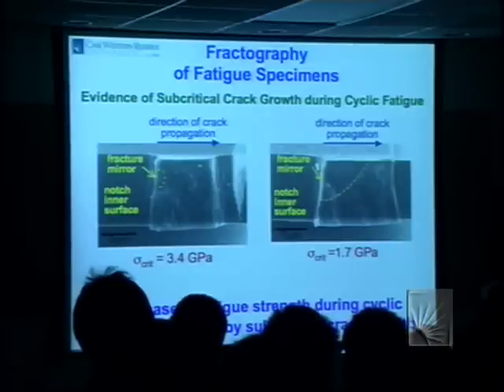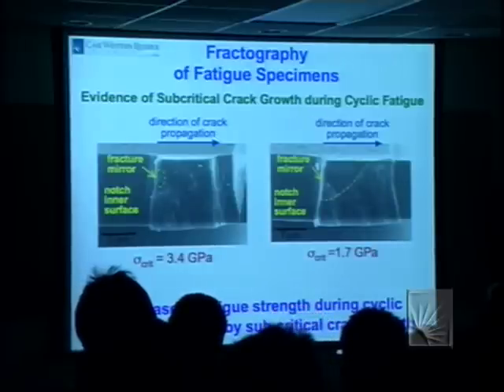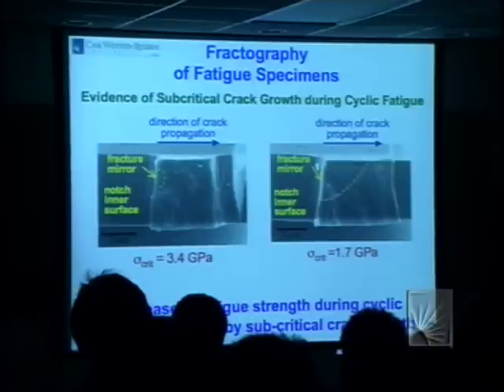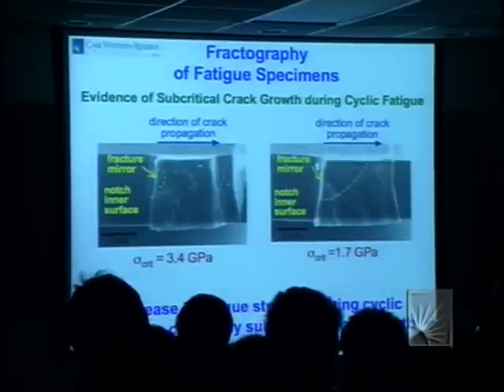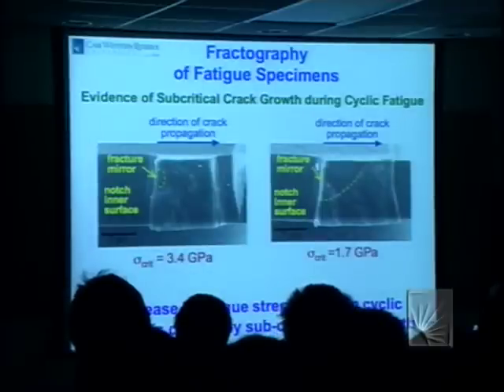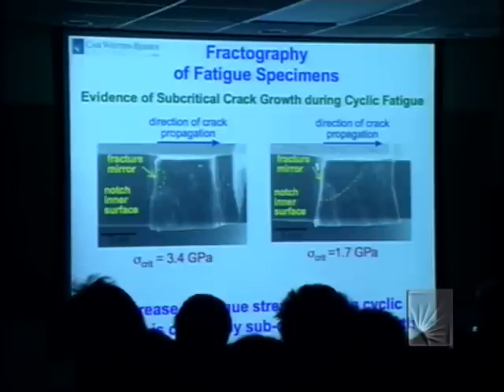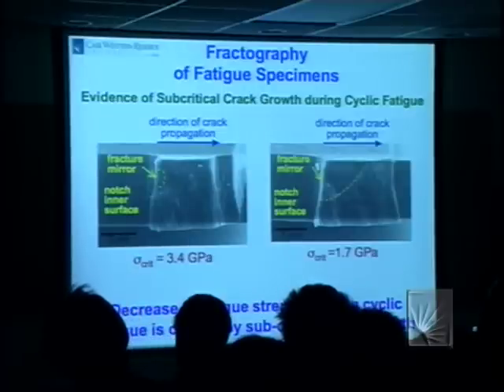The flaw itself that's present is not large enough, not severe enough, to cause fracture at this stress, and you have to wait until the flaw grows. There's an inverse relationship between the fracture strength and the size of the flaw. The larger the flaw, the smaller the strength. So there must be some mechanical damage.